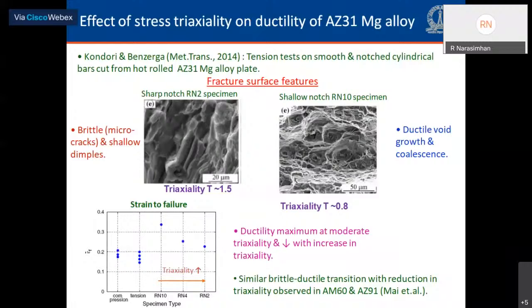On the other hand, if you look at the right side micrograph, which pertains to a shallow notched Rn10 specimen, which has got a lower triaxiality of around 0.8, we see ductile void growth and coalescence. So there is a transition in the fracture mechanism as the triaxiality decreases. Also, the bottom figure shows the strain to failure. And we can see the strain to failure is maximum corresponding to moderate triaxiality, Rn10 specimen, around 35% ductility, and then it decreases very sharply with the increase in triaxiality.